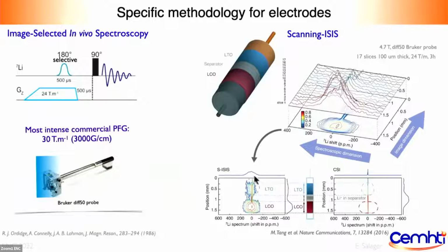So it was an oxide, lithium titanate oxide and lithium cobalt oxide. These are the two electrodes. And if you do chemical shift imaging, so this is the Z position, this is the spectrum. If you run standard echo-based chemical shift imaging, then the only thing we can see is the electrolytes inside the battery. So we worked on using these strong pulse gradients, and also we went back to smart techniques that